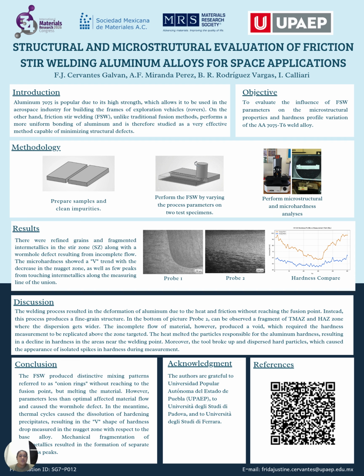On the other hand, friction stir welding, known as FSW, unlike traditional fusion methods, performs a more uniform bonding of aluminum and is therefore studied as a very effective method capable of minimizing structural defects. The objective of this investigation was to evaluate the influence of FSW parameters on the microstructural properties and hardness profile variation of the aluminum 7075 T6 weld alloy.